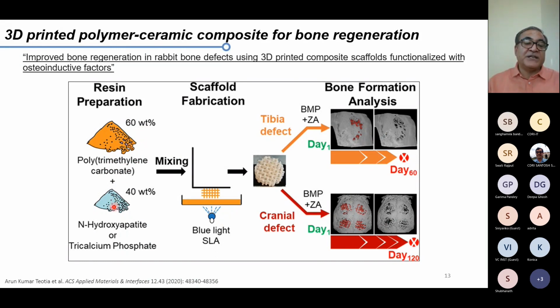Then you have the hydroxyapatite in-house, or you have tricalcium phosphate. You mix both the components and then do stereolithography. By that, you can construct the scaffolds, what I am showing here, honeycomb type of scaffolds. We used that in tibia defect and cranial defect in the rabbit model. In both of them, we added BMP and ZA.